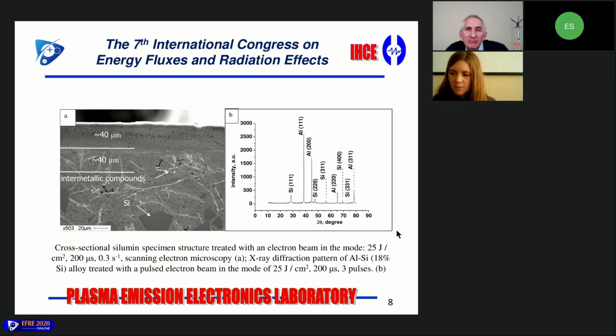Olga Krisina has the next question. Is it possible to enhance the properties of the silumin that you have got? Yes, we can alloy. For example, we can deposit a coating. We can alloy our material with our electron beam. At first, we use, for example, titanium or zirconium, and we deposit it on our surface, and then we melt it with our electron beam. So we can get better properties than we have.